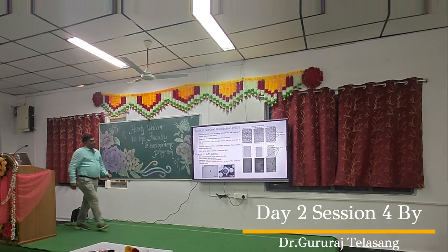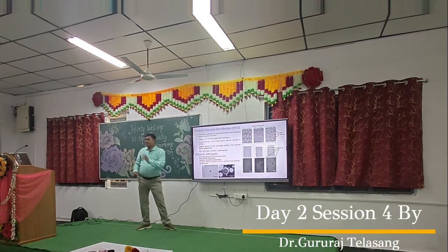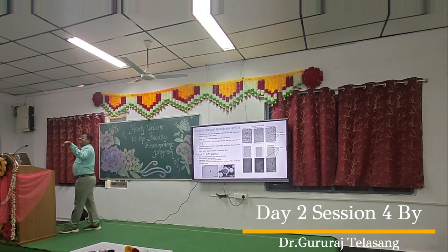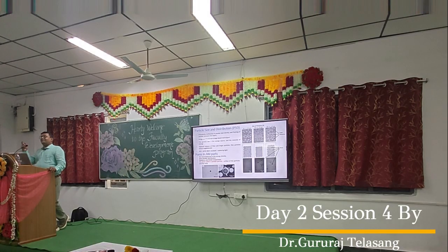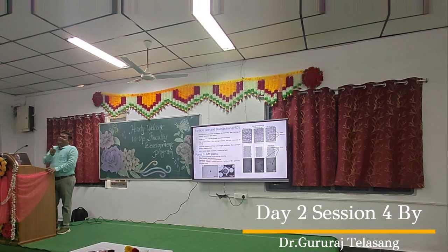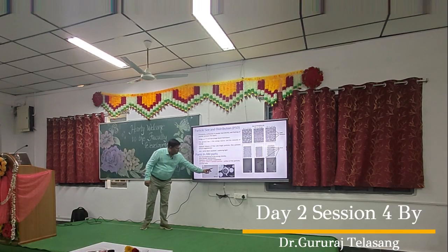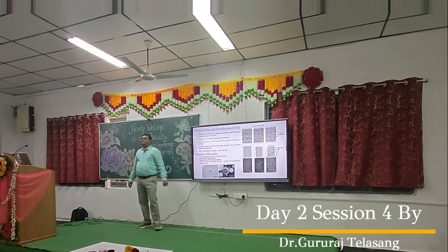This is another particle. It is hollow inside. That is gas entrapped in the particle itself. And if I use such a powder in my process, that gas will still be entrapped in my component, and you will see it as a perfect spherical porosity. If there is a perfect spherical porosity in the cross section of additive manufacturing, that is gas entrapped. If it is non-spherical, you can improve it. But if it is perfectly spherical, you have to check your powder, or check your inert gas flow, or change some parameters. Can you see here, perfect spherical? These are mostly from such a powder.